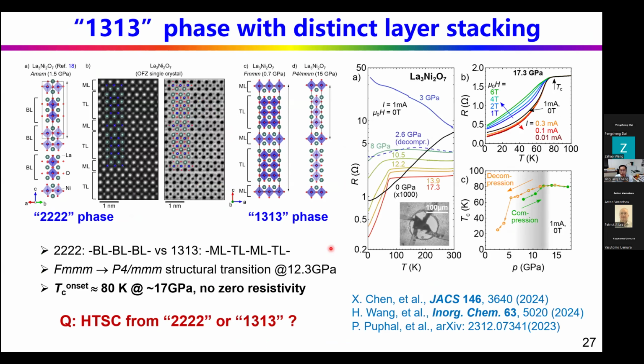In addition to the conventional bilayer phase, this 2-2-2 phase, which 3 groups independently reported, actually there's another competing polymorph, the 1-3 phase. This phase consists of the alternating growth of the single layer, monolayer, and the trilayer. So this is the 1-3 phase. And for this 1-3 phase, high pressure resistivity measurement also shows the appearance of a resistivity drop around 80 Kelvin. But also there's no zero resistivity.